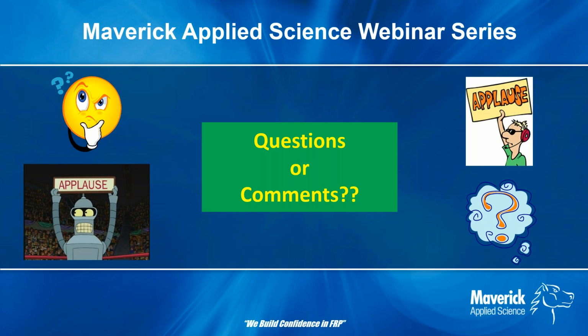Okay, good. Next question, is the laminate analysis a progressive failure analysis or a first ply failure analysis? Oh, brother, this gets filed in the, I'm not going to answer it to your satisfaction. So I mean, this is very, very into the weeds for very, very smart and technical people who really understand laminate analysis. I'm claiming to be maybe in the middle range of not knowing anything and knowing everything. To me, first ply is bad. If you fail that first ply, it's usually that inner layer. It's usually the weakest one, which is the very inner layer that has the highest resin content, which means lowest reinforcement. So you start failing that because you're overstressed.